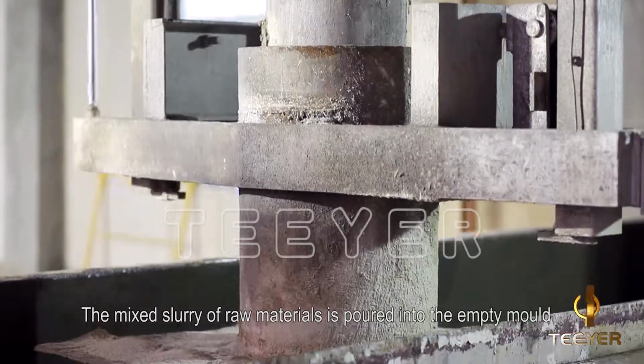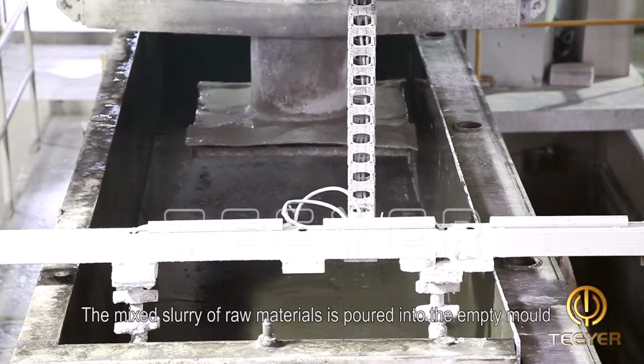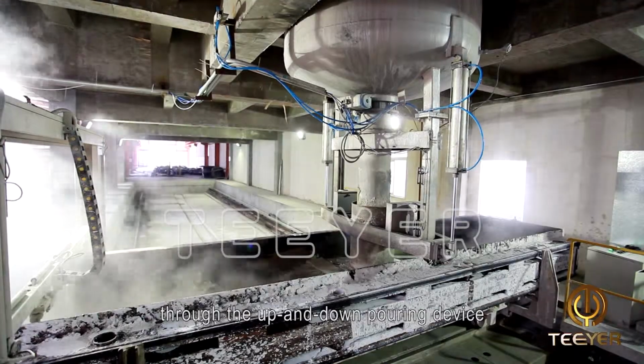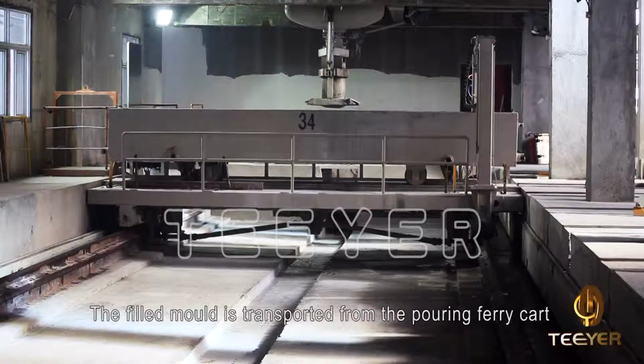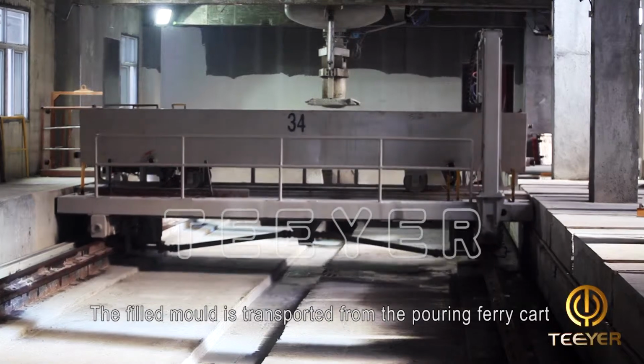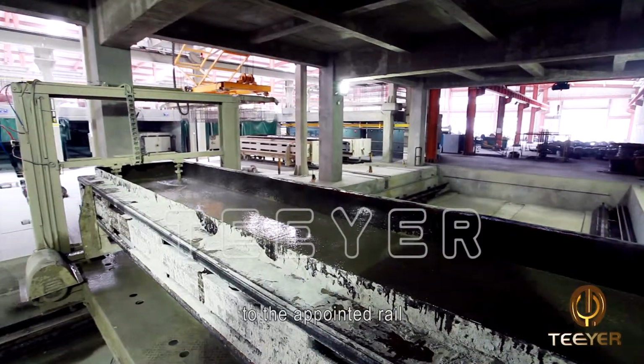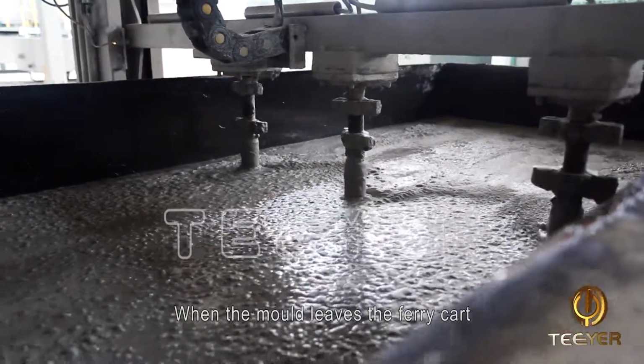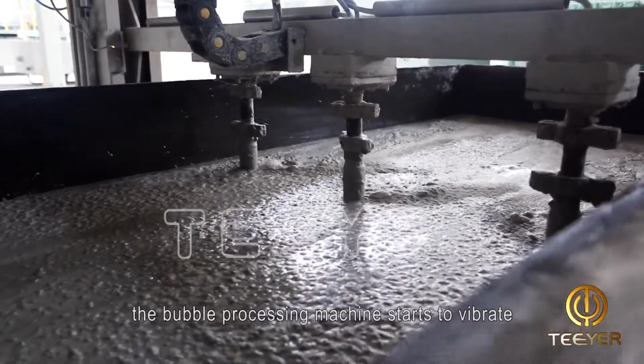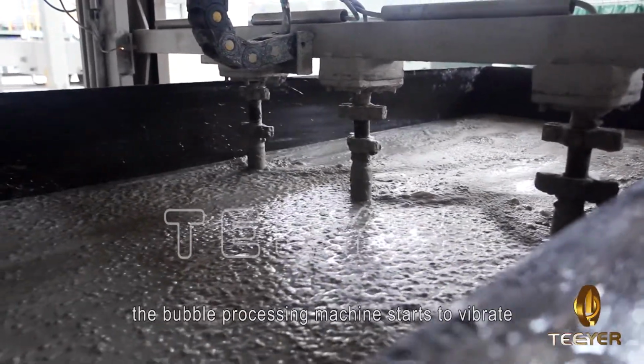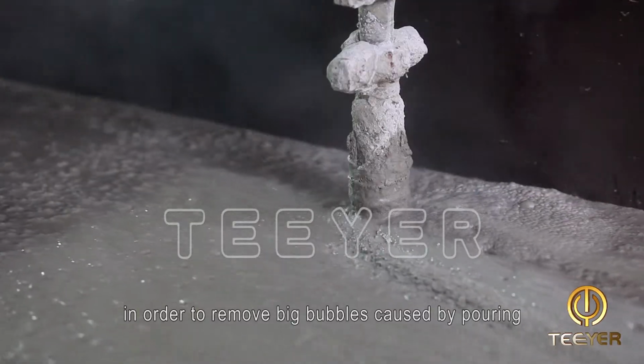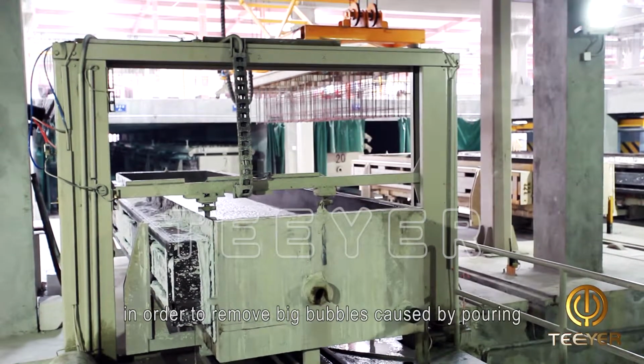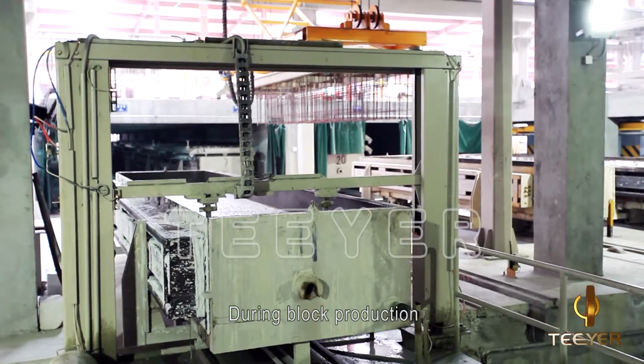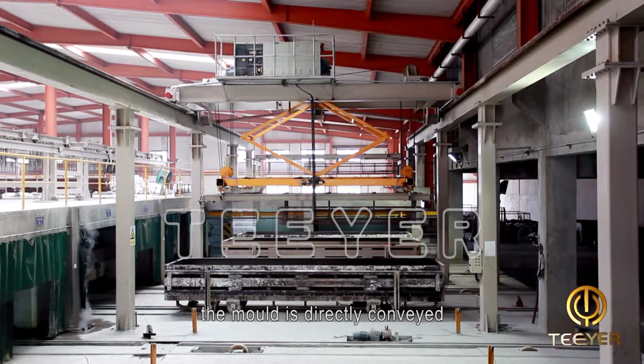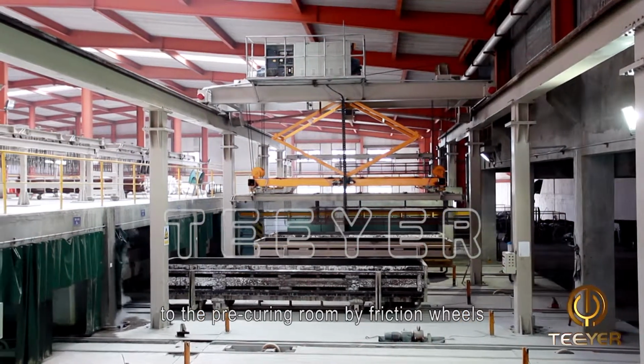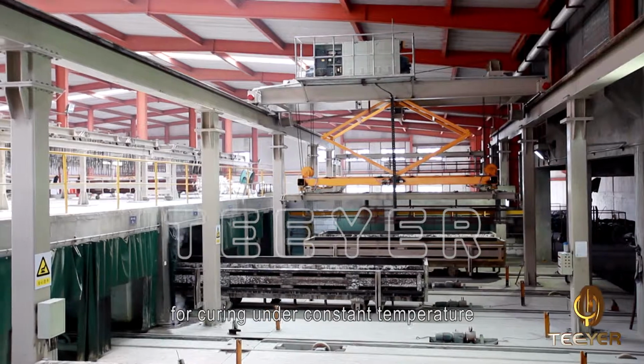The mixed slurry of raw materials is poured into the empty mold through the up and down pouring device. The filled mold is transported from the pouring ferry cart to the appointed rail. When the mold leaves the ferry cart, the bubble processing machine starts to vibrate in order to remove big bubbles caused by pouring. During block production, the mold is directly conveyed to the pre-curing room by friction wheels for curing under constant temperature.